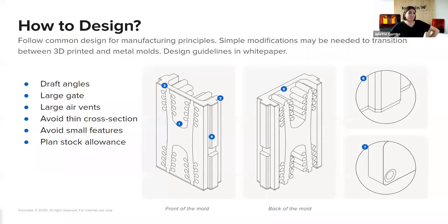So the first step is to design the mold. At Formlabs, we are experts in additive manufacturing, but we are not experts in mold design. But we've been working with experts in injection molding, and they gave a lot of different recommendations on how to minimize the impact of the pressure in the cavity. That's really one of the best ways to increase the longevity of the mold. So in the white paper you can find a lot of recommendations on, for example, increasing the draft angle. 2 to 5 degrees, for example, is really the best.